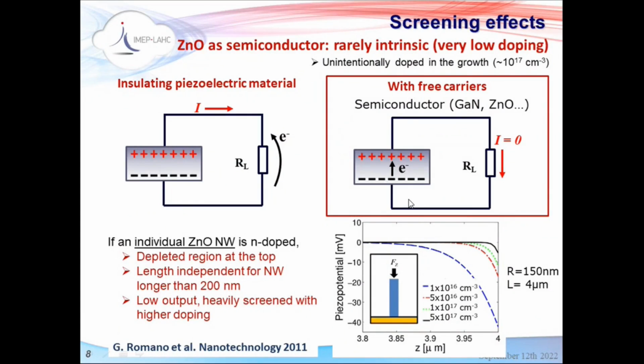And this kind of behavior was simulated in the past by several groups. So here you have only a single nanowire under pressure, consider only doping, and you can see the potential that is generated. It is very low, in the order of millivolts. And what they found is that this potential is concentrated at the top of the nanowire. So this is 4 micron long. So everything happens here at the top of the nanowire, and it is very small for typical doping concentrations.